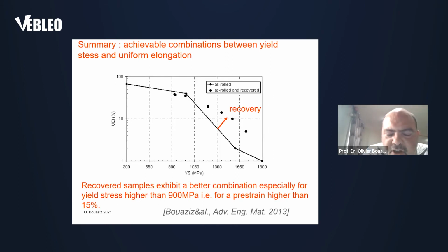So it is a summary chart showing the difference between pre-strain, in diamond, as a function of the evolution of uniform elongation as a function of YS without recovery treatment, so diamond here. And this is the result after recovery. So we escape from the banana curve, showing the usual decrease in uniform elongation as a function of YS.